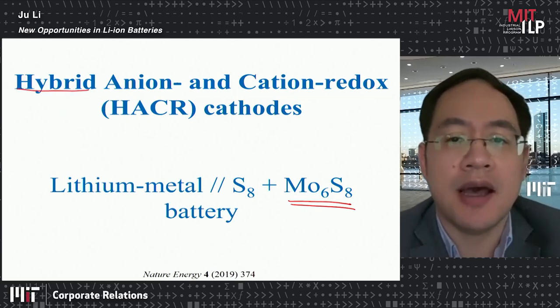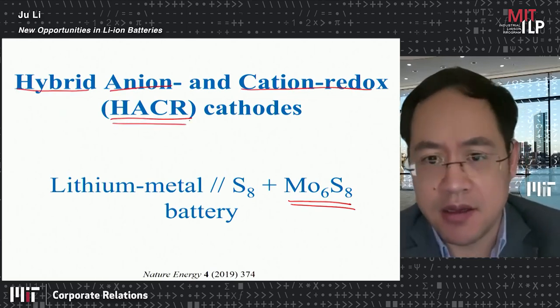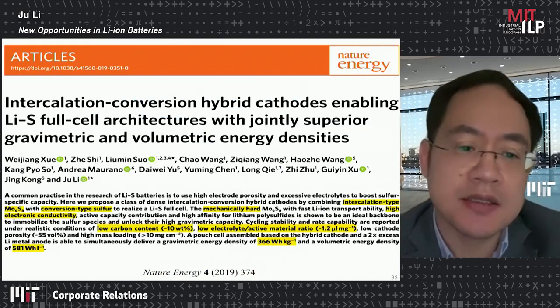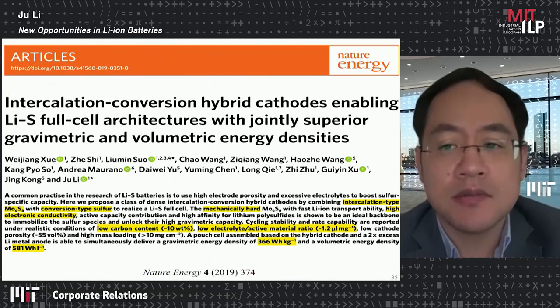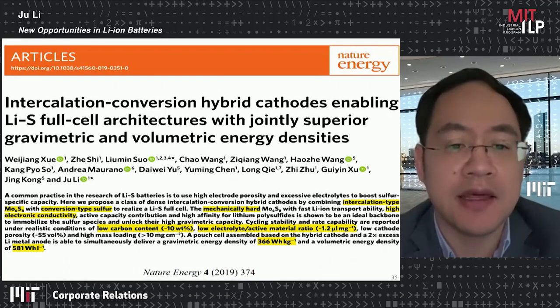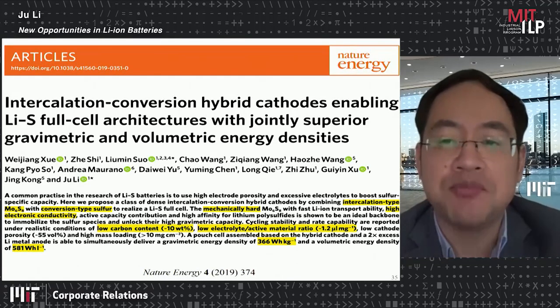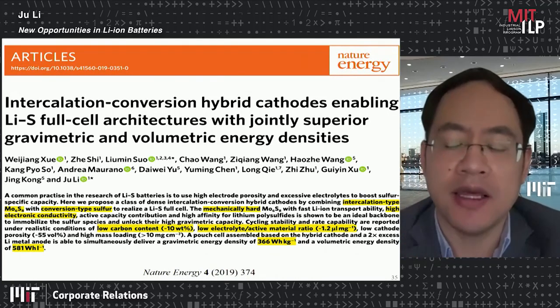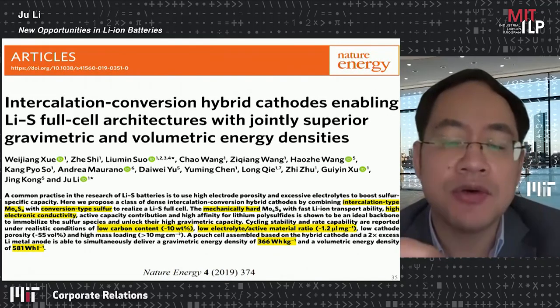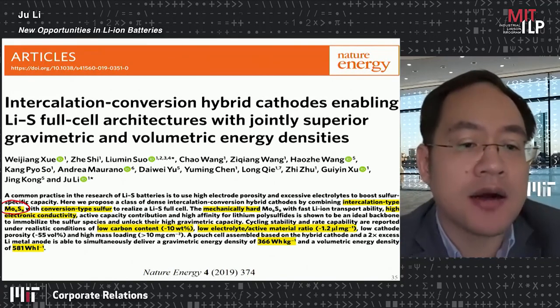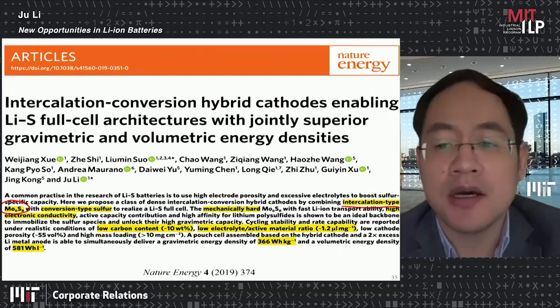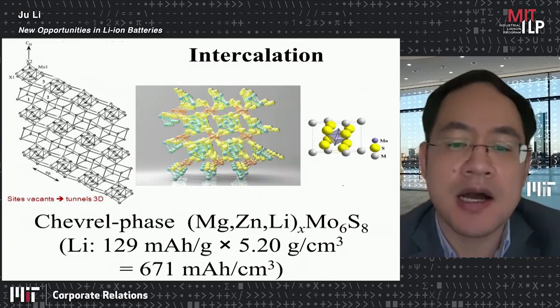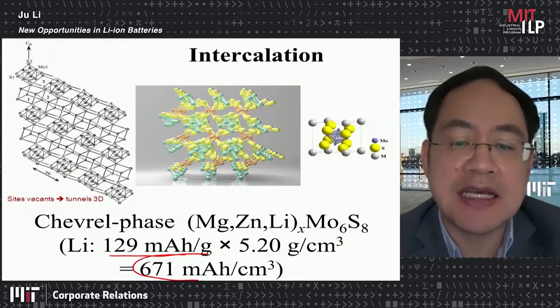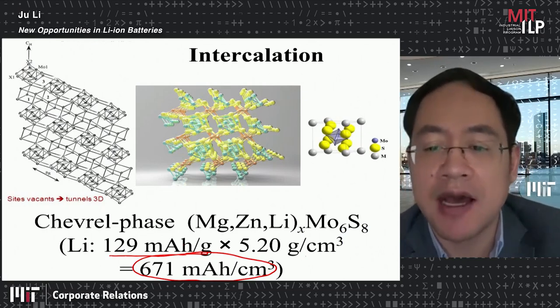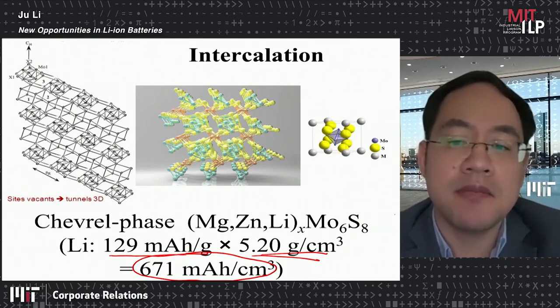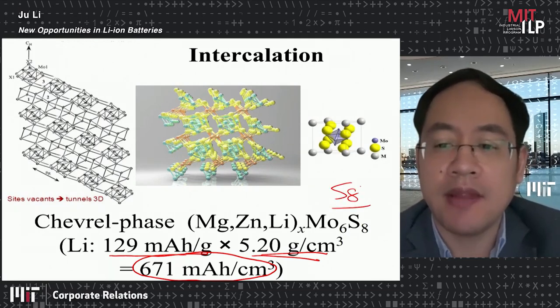So this is what I call a hybrid anion-cation redox, abbreviated as HACR, cathode concept. In this case, we're mixing traditional sulfur, which has low conductivity and high porosity, and is actually pretty bad in terms of making slurry coatings. It has pretty bad rheological properties. It's very difficult to have high compressed density in this system with this very hard, very dense intercalation-type molybdenum sulfide, which contributes this much capacity and actually has a pretty decent volumetric energy density because of the high density. So we're mixing them with sulfur 8 and this composite